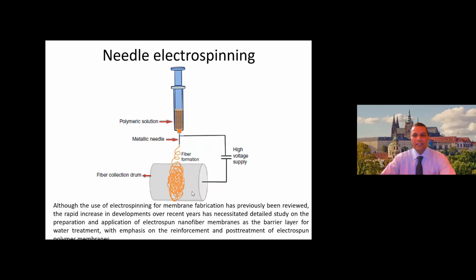This distance and the voltage decide what the diameter of the fibers will be, especially since the diameter is not uniform. Why? Because we do not have any positive control over the diameter by stretching or drawing as in conventional spinning; it is just random deposition of fibers. That is why the diameter may range from a few nanometers, less than 10 nanometers, to some 100 nanometers or 500 nanometers. Thus, the variability of nanofibers in this method is definitely a matter of concern. It can be minimized by consistent viscosity, concentration, voltage, and distance